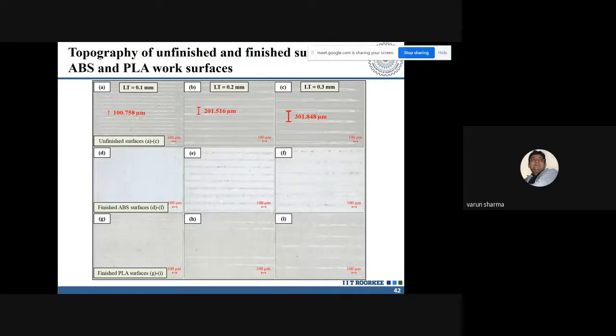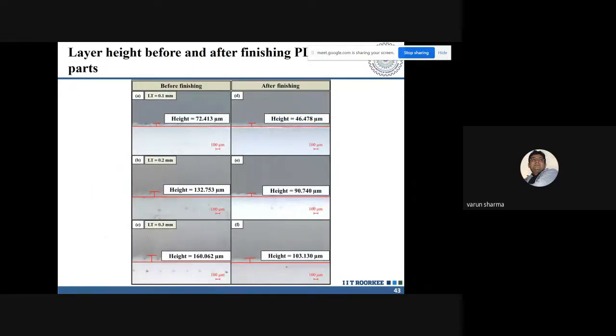Now as you moved from, for the ABS, what you see is that the furrows that were easily visible over here have already gone away. Fine. For 0.2 it was less, for 0.3 they were still visible. So for the 0.1 mm layer thickness, a better surface finish has been achieved for the ABS as well as for the PLA in this particular context. Now when you look at the cross-sectional view, see over here that this is the material that was being stacked over here.